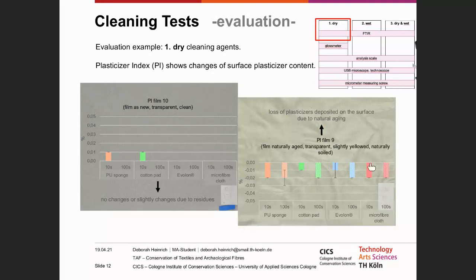Here is an example of the evaluation of the first test on dry cleaning agents using the FTIR measurement. The peak intensities of the CH group of the PVC and the plasticizer in the FTIR curves before and after cleaning can be put into relation. From this, the plasticizer index, PI for short, is calculated. The PI shows changes in the content of plasticizer on the surface in percent due to, for example, cleaning. The percentage of the PI refers to the plasticizer content measured before the treatment.